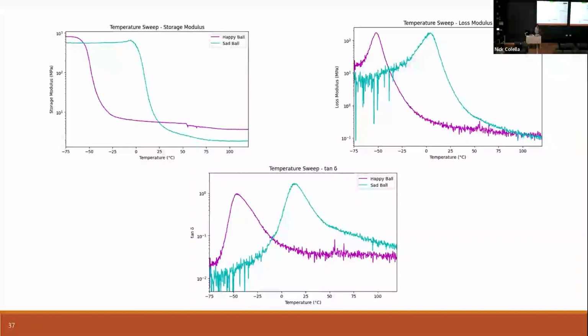And almost all polymers will have some glass transition temperature, above which they're rubbery and below which they're glassy. For the sad ball, we see that the actual glass transition temperature is right around 15 degrees Celsius, which is close to room temp. So when we're bouncing it, it's kind of at its glass transition point. And that's the key for why it has some different mechanical properties.